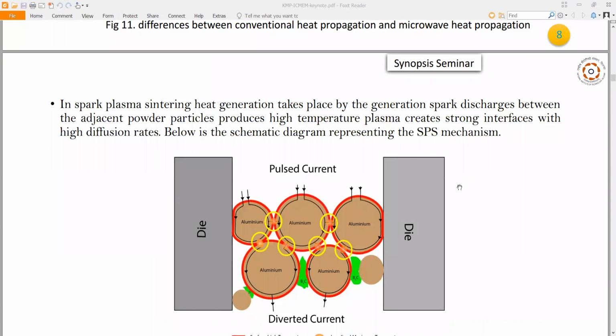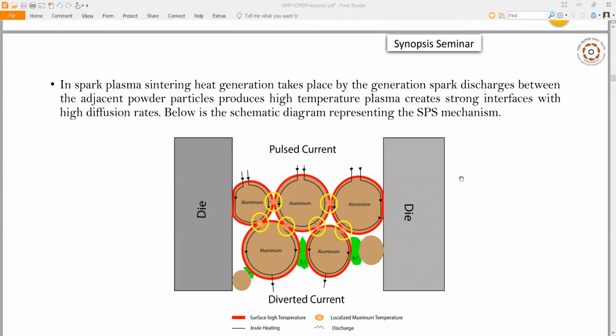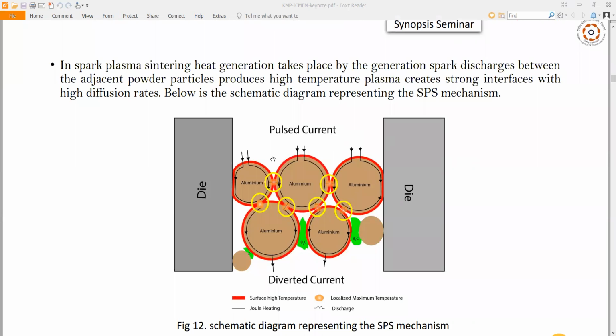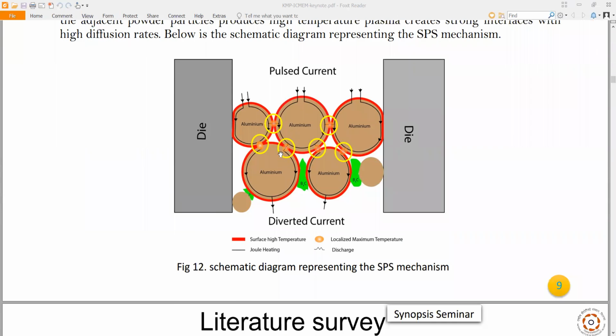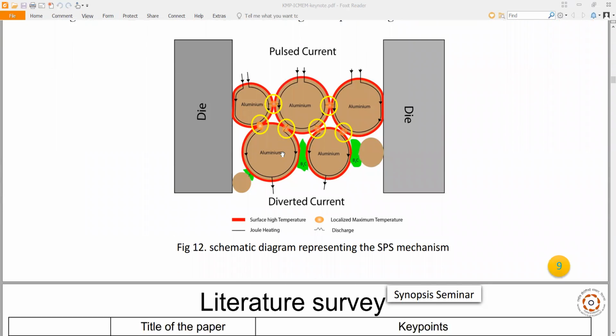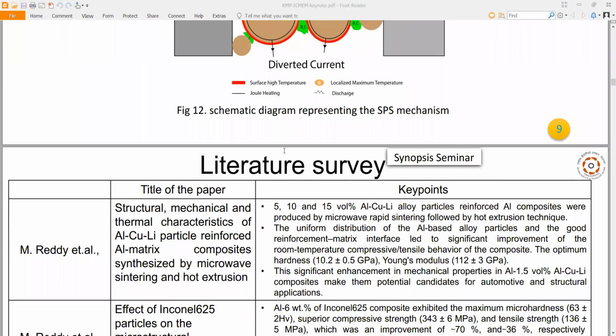Then, in spark plasma sintering, heat generation takes place by spark discharges between the adjacent powder particles, producing high temperature plasma, which creates strong interfaces with high diffusion rates. Below is the schematic diagram representing spark plasma sintering. Here we can see the pulse current, and this is the die and diverted current.